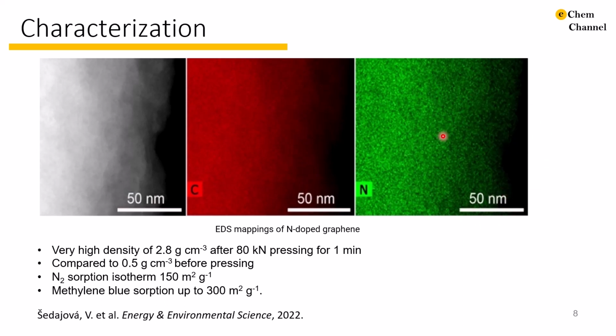What is also extraordinary about the GN3 material is its very high mass density of 2.8 gram per cubic centimeter, compared to only 0.5 gram per cubic centimeter before pressing. The BET surface area yielded 150 square meters per gram, and the methylene blue sorption yielded a surface area of 300 square meters per gram.